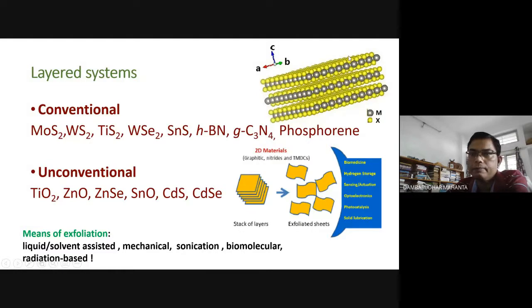So in-plane bonding is very strong, and out-of-plane bonding is weak, which is van der Waals bonding. Layered structures which appear in the form of layers include MoS2, WS2, TiS2, WSe2, SnS, hBN, g-C3N4, which is called graphitic carbon nitride, and phosphorene. These are put in the conventional category because they exist with a stack of layers, whereas unconventional means they do not exist in layer fashion.